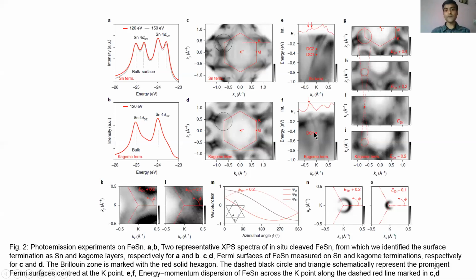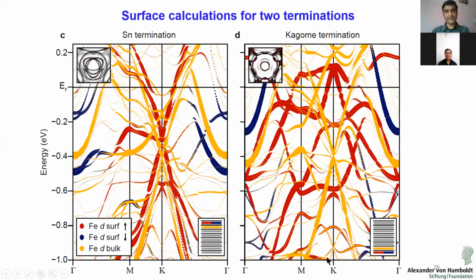Based on that, we consider the surface calculation from our DFT, and we could see that when it is Sn termination, we observe what is found in experiment, where you can see red and yellow. So there are two Dirac cones appearing in this feature. And in this case, you can see that there is one Dirac cone in kagome termination. These are the positions which I will not discuss because of the time.